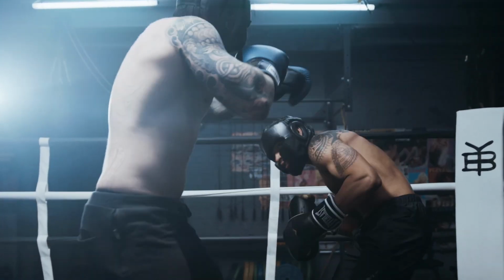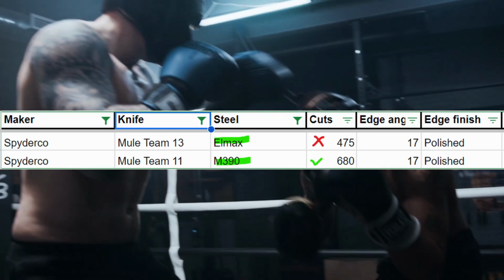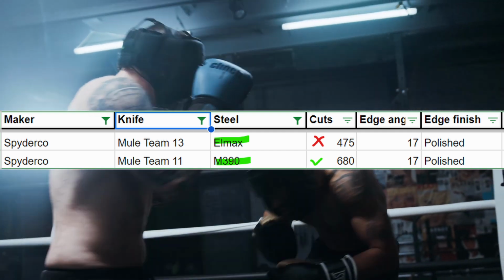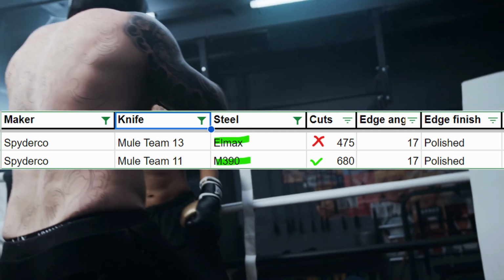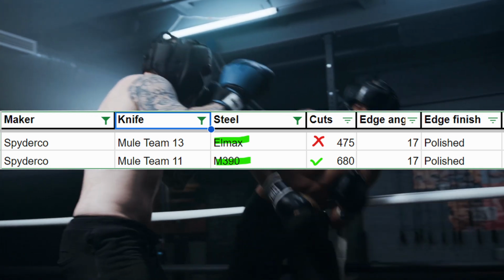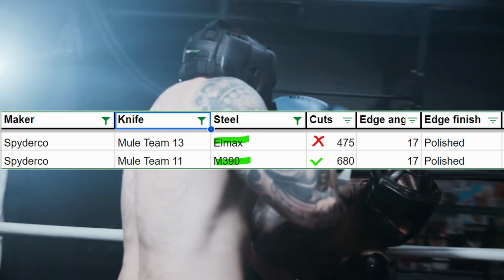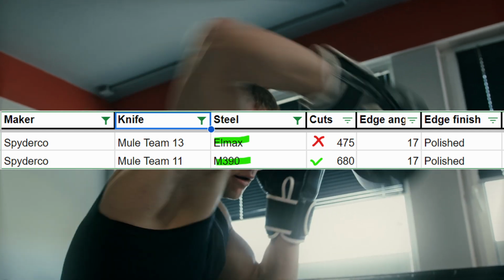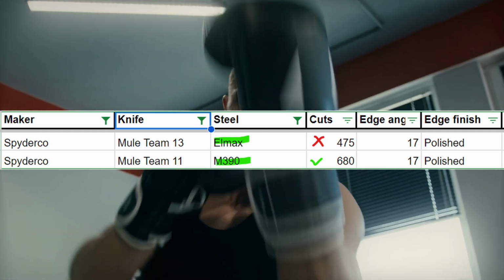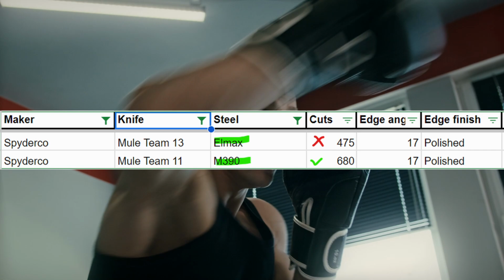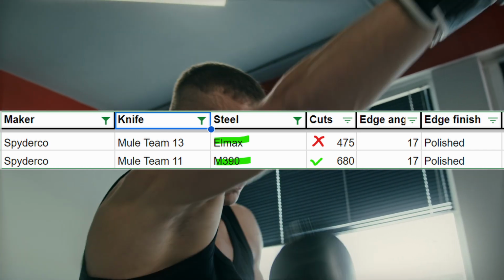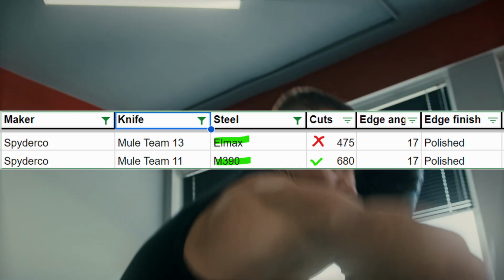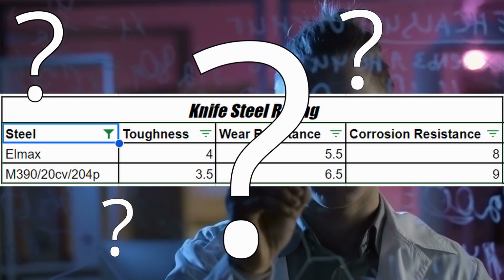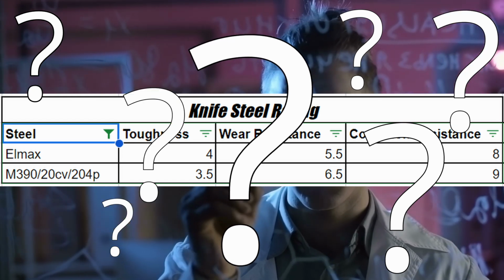Lucky for us, we can make this comparison by comparing the Spyderco Mule Team knives in Elmax and M390 respectively. This may come out as a bit of a shocker, but while the Elmax Mule performed 475 cuts at 17 degrees, the M390 Mule Team performed more than just marginally better with 680 cuts at the same 17-degree angle, a large margin of victory by about 205 cuts. So if Elmax is only supposed to have slightly less wear resistance than M390, why did it get thrashed in the cut test by the M390 version of the exact same knife by such a large margin?